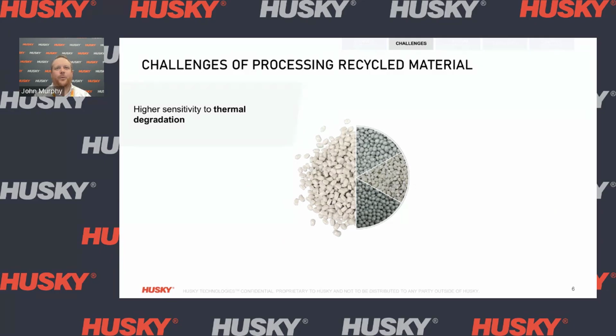As the industry moves more and more towards processing of recycled material, we need to first be aware of the challenges this material presents. rPET resin is more sensitive to the drying temperature it is exposed to. Exposure at a high temperature for a long period of time can cause yellowing of the material, which is caused by thermal degradation. rPET material is also susceptible to condensable contaminant generation, predominantly when exposed above 160 degrees Celsius. Condensable contaminants can affect the performance and consistency of the desiccant dryer. Effective removal of condensable contaminants supports the highest preform quality.